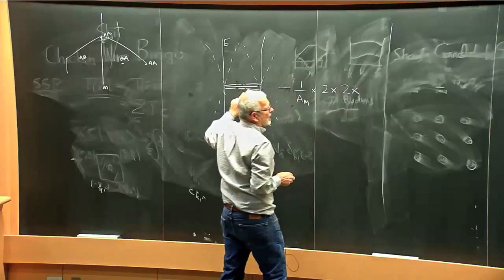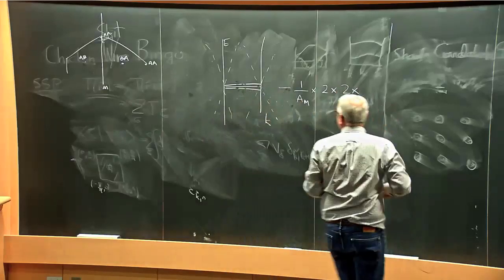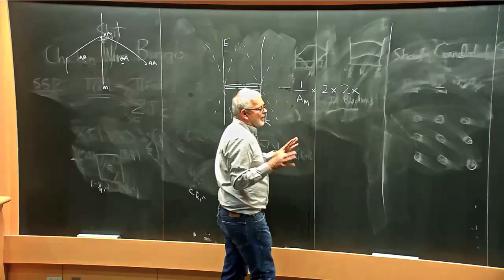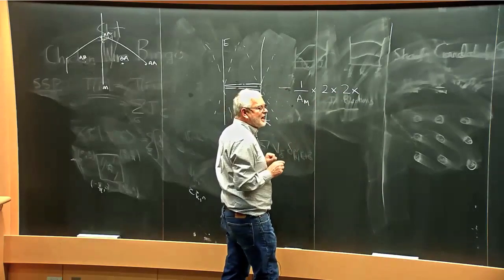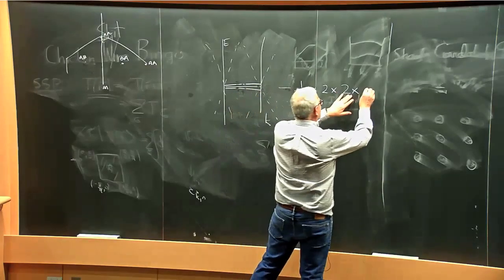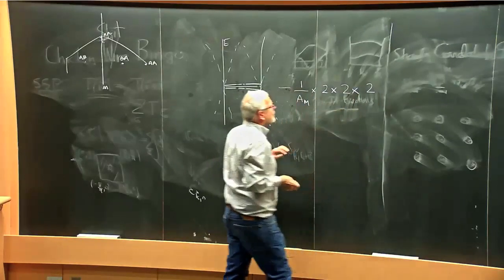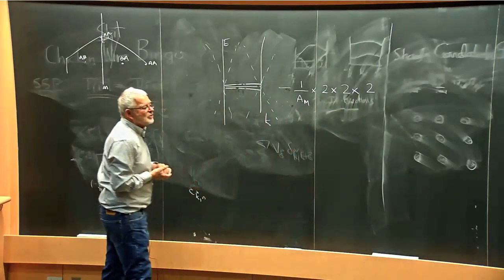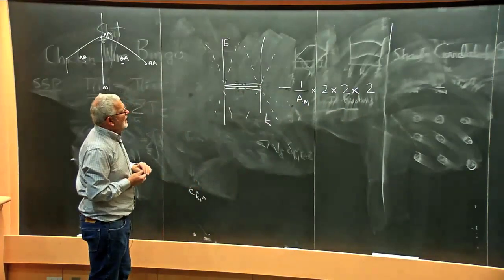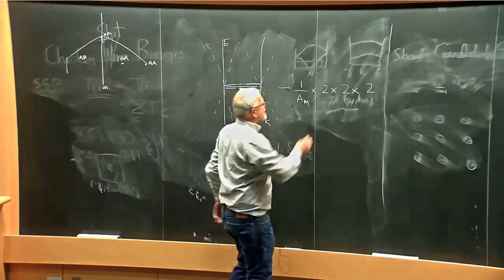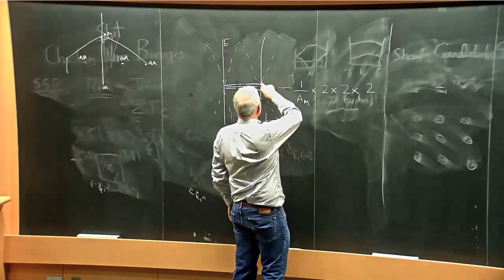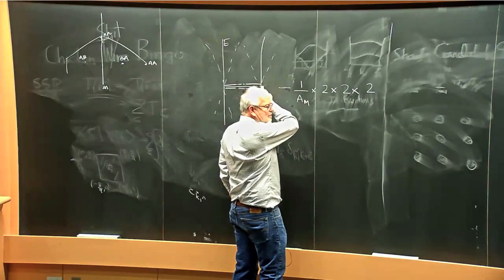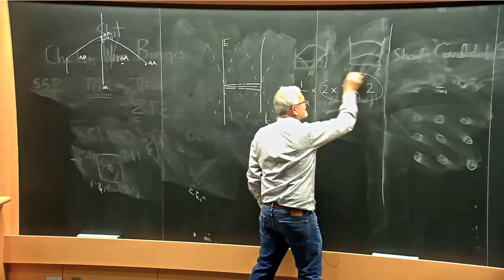And I said that the crossing low energy states occur at the momentum honeycomb lattice Brillouin zone corners, and it turns out there are 2 independent ones of those. So that means instead of 2 internal labels for these flat bands, you have 8.